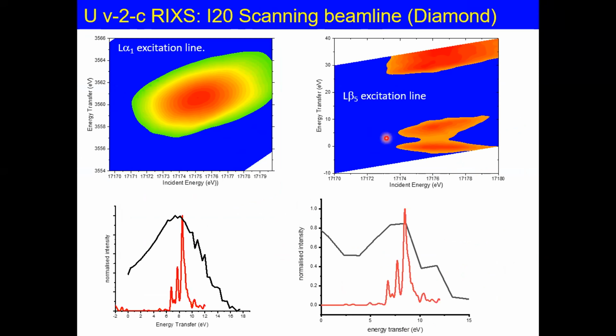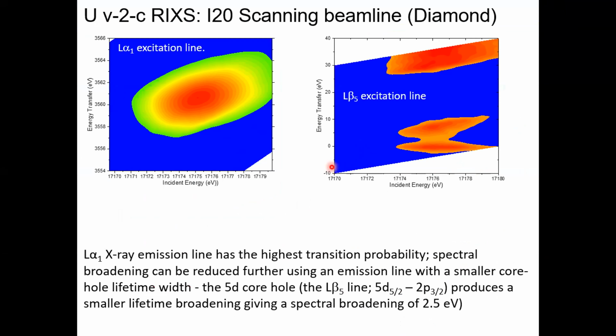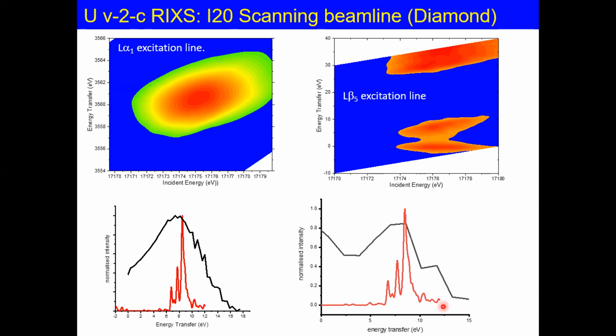So on the right side, this is written L beta 5 excitation line, but the energy transfer is in the order of a few electron volts. So is it the energy transfer was shifted, or is it a valence band RIXS? I think this was the energy transfer. We have the valence band RIXS as well, but we haven't delved in too much detail on that one yet. Because L beta 5 is 100 eV below the absorption edge. And as soon as the energy transfer is only a few electron volts, I was wondering if this one is the valence band, or is it really the L beta 5 line? Good question. I think I've reached the limit of my knowledge of RIXS for sure.